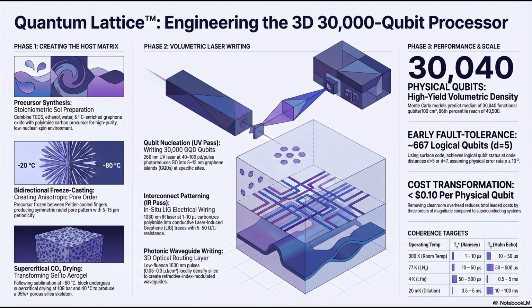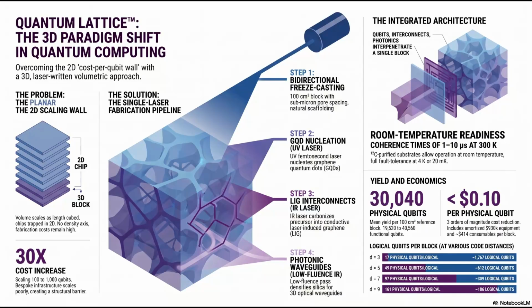We don't have to take the block out of the machine. Wait, really? It just stays on the stage? We don't have to move it to a clean room to apply photoresist or etch metal. We keep the aerogel block exactly where it is, on the exact same galvo stage. Okay, so we use the ultraviolet laser to nucleate the qubits. Now what? The system simply switches to a different laser head. It uses a high-fluence infrared laser, specifically operating at a 1030 nanometer wavelength. It pulses with a higher energy than the UV laser, between 1 and 10 microjoules per pulse.